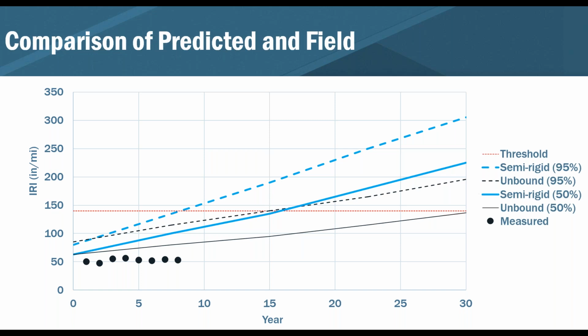So in this graph, again, it's a little bit on the busy side. The red dashed line at 140 inches per mile is the threshold value they used in the PMED. The light blue lines represent the model if run as a semi-rigid layer, the dashed line representing the 95% and the solid line representing 50% reliability. And then the black dashed line and black solid line are if you run the analysis with the FDR as an unbound stiff layer. And you can kind of see the difference. And again, reflective cracking, I believe, is driving a lot of the increase in IRI in the semi-rigid analysis versus the unbound analysis.